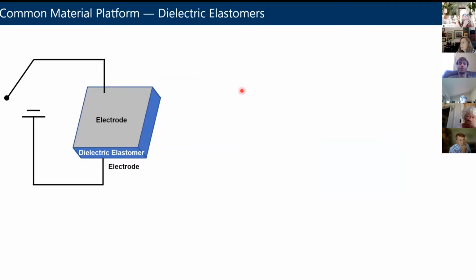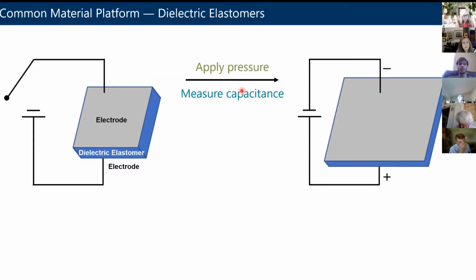type of device we probably learned about in introductory physics all that time ago. If you take 2 electrodes and in between you put some material, which is a dielectric, you can control the capacitance of this device through the thickness of the elastomer, or the dielectric, in between. And if you make the dielectric an elastomer, meaning it's deformable like a rubber band, you can apply pressure to the electrodes. You can physically deform the device and make the electrodes squish closer together, as depicted on the right. And you can measure that change in capacitance because the thickness of that dielectric layer changes.